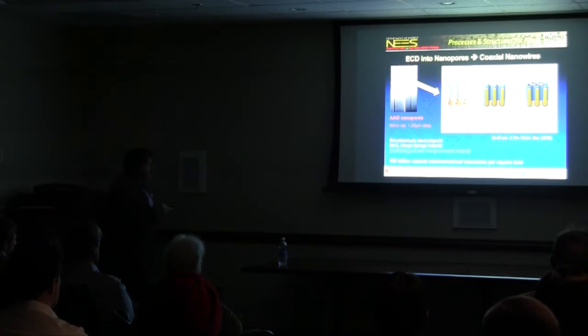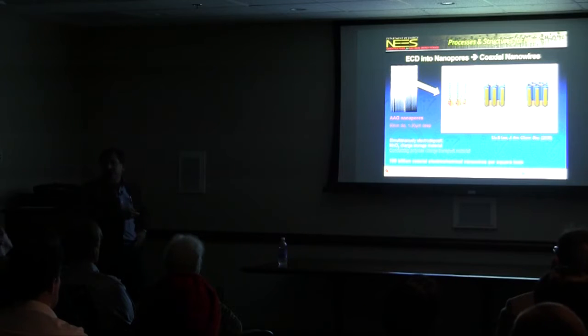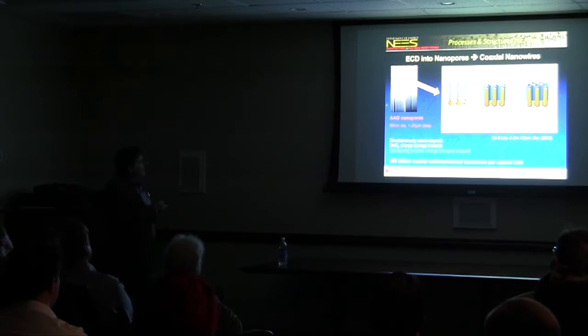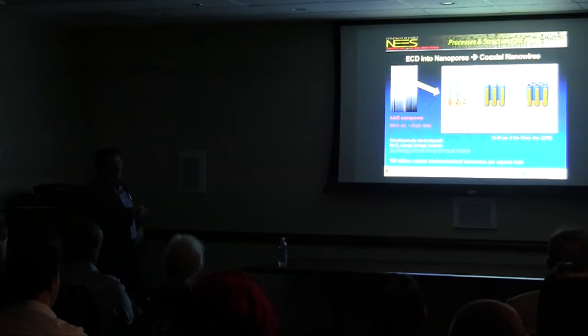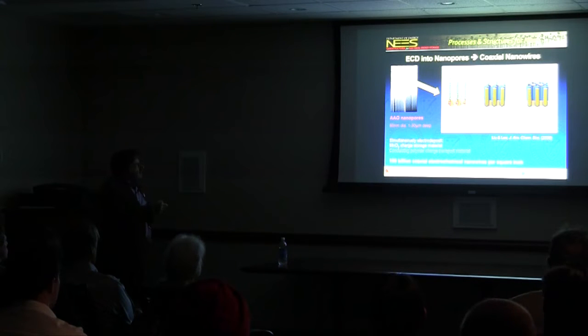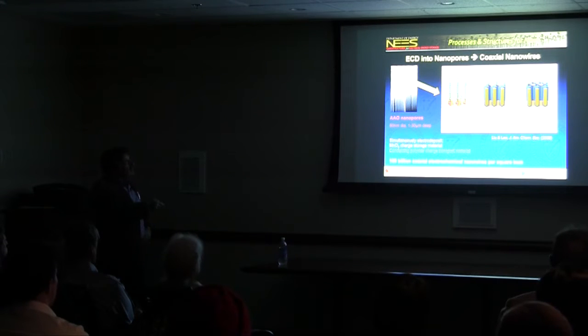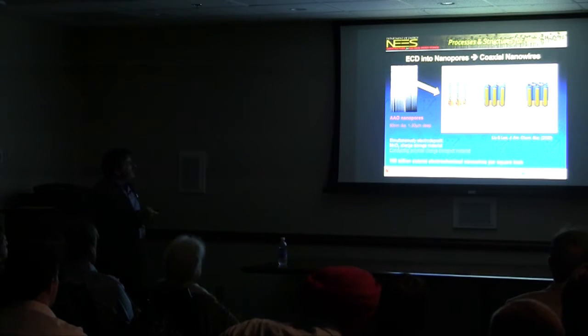So my collaborator, Sangkook Lee, has done some wonderful work which really led us into this whole energy-centric business. He took this kind of structure, electro-deposited two materials, manganese oxide, which is a good storage material, and PEDOT, a conducting polymer that helps the electrons get where they need to go, because you've got to move both ions and electrons. And he made this co-deposition into the pores, then removed the anodic aluminum oxide template to have these exposed coaxial nanowires. And their performance is really exceptional.